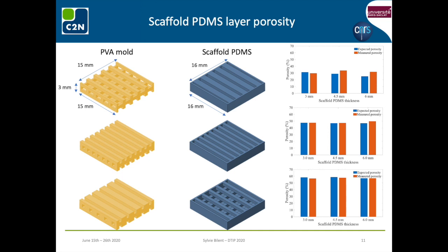The porosity of these samples were estimated by design using the 3D geometry of the scaffold and the density of PDMS. The porosity was also experimentally estimated after fabrication. Here, you can see the estimated porosity for every channel arrangement as a function of the sample thickness. One can note that the expected porosity in blue and the obtained porosity in orange are very similar, less than 4% difference. Here, the chosen scaffold designs enable PDMS samples of around 30%, 50%, and 60% to be produced, with an easy and highly reliable porosity tuning method.